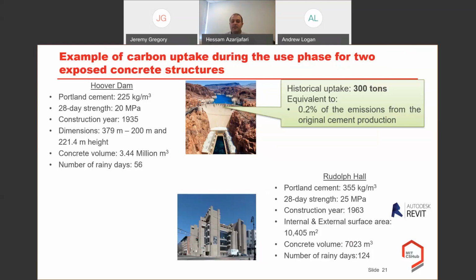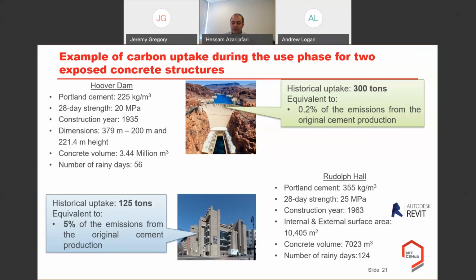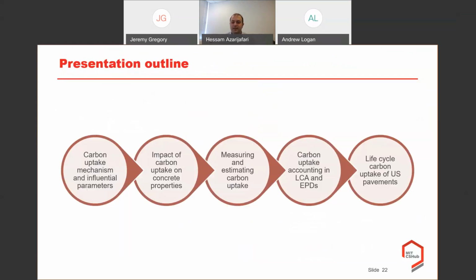And based on the conditions and the number of rainy days that we had in Connecticut, we could estimate that the total amount of uptake since 1963 was around 125 tons CO2, which is equivalent to 5% of the emission from the original cement production. So these are some calculations for the use phase carbon uptake of some concrete elements. But what is more important for us, that we have done and already published, is the life cycle carbon uptake of the US pavement network.